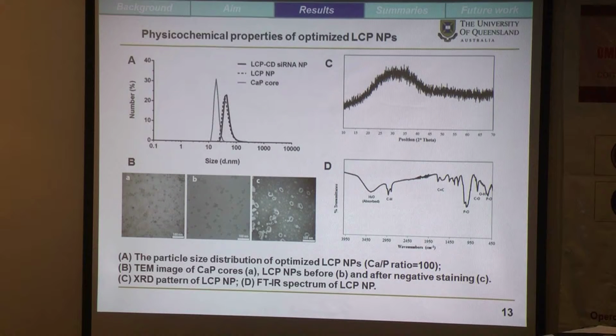These are characteristics of the optimized LCP nanoparticles. Shown in the picture, the size of the calcium phosphate core is about 20 nanometers. And the size of the LCP nanoparticles increased to 40 nanometers after coating the second lipid layer. When loaded with the functional cell death siRNA, the size remained unchanged, with the zeta potential of minus 15 millivolts.